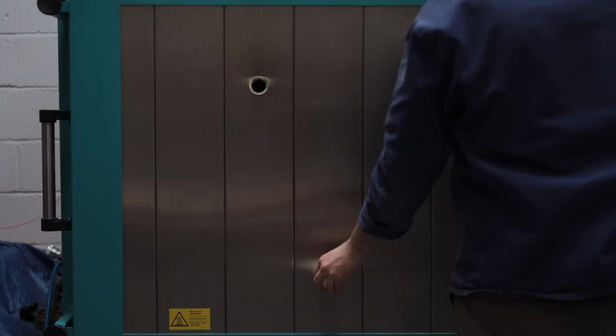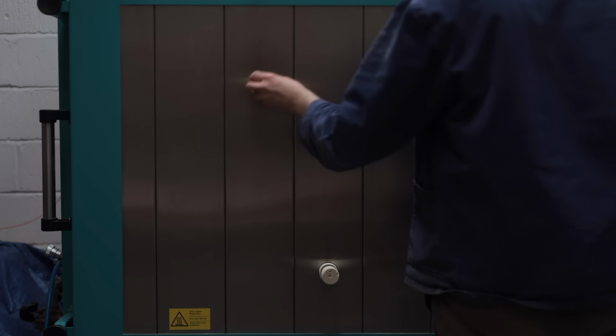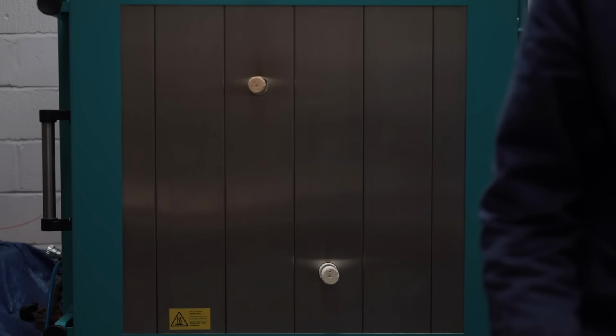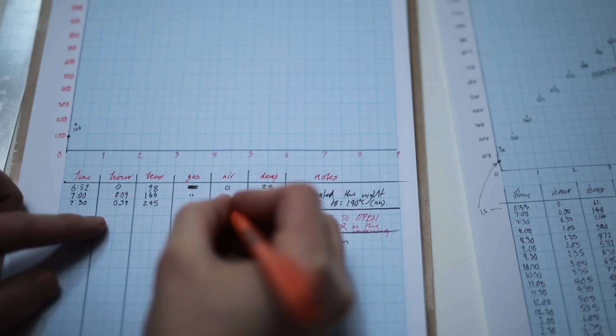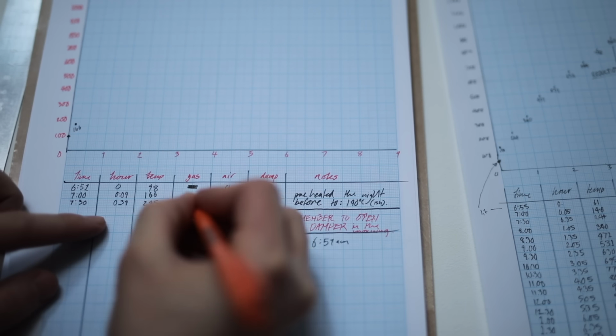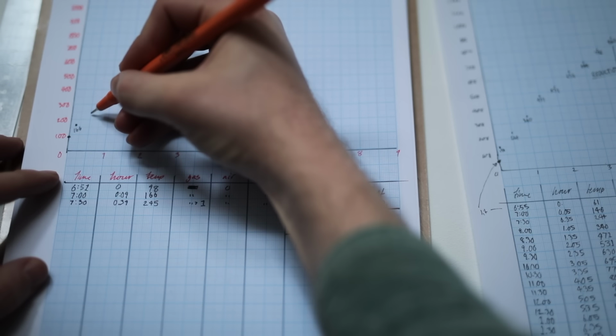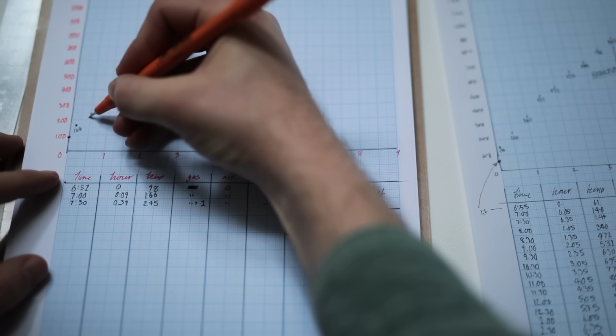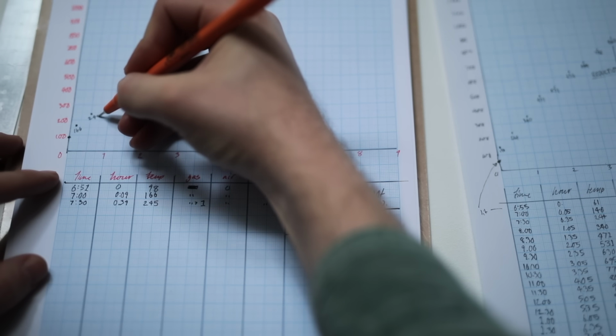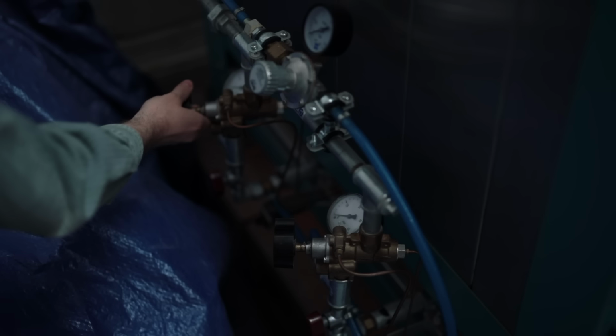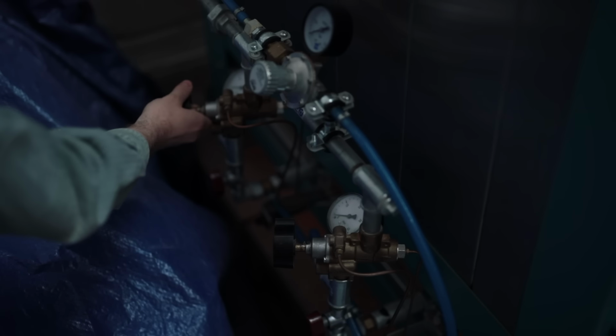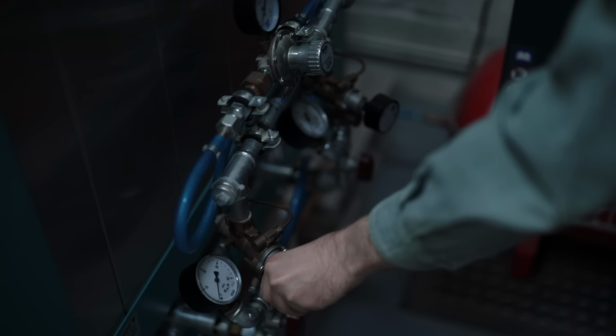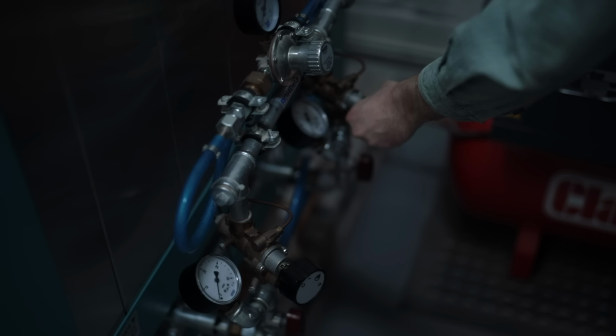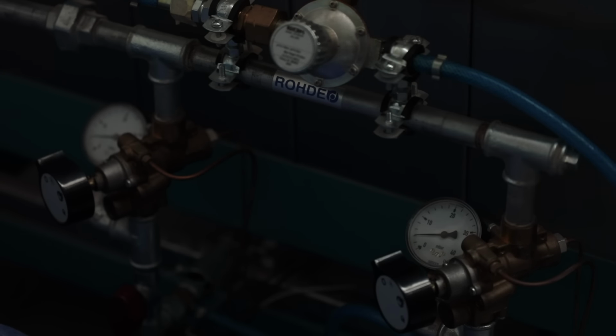The glaze firing begins at 7 o'clock in the morning and typically takes about 8 to 8.5 hours to complete. Every 30 minutes I log the time, hour, temperature, gas, air and the damper position, and then I place the temperature on the graph above, which helps me see if the temperature is rising up too quickly or too slowly, and it gives me a good curve to follow in subsequent firings. I take it slow initially, as if you very rapidly increase the temperature, the pots inside, in certain situations, can explode, bursting almost, scattering shards everywhere.